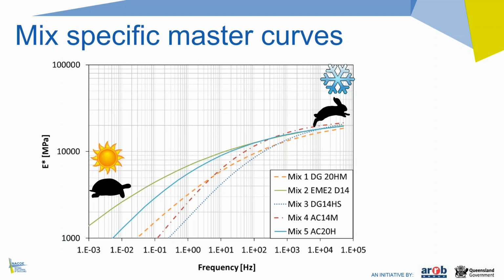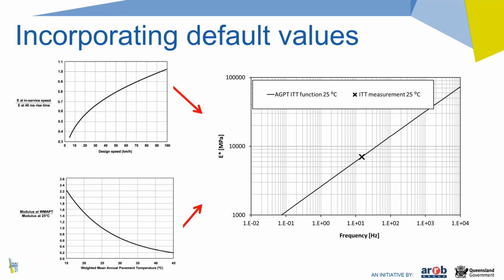What we can also do is incorporate default values. So the current TMR design supplement has default values for different mixes, and what we have done is convert those correction factors in Austroads for temperature and load frequency. You can convert those into a master curve. So the graph on the right shows you if you take those two Austroads correction factors for temperature and load frequency, you can come up with a master curve to cover them both, and you can still use resilient modulus results and then put those values into a master curve.